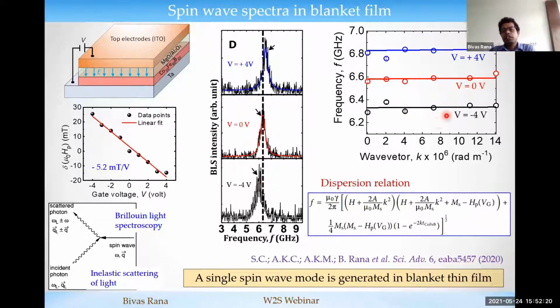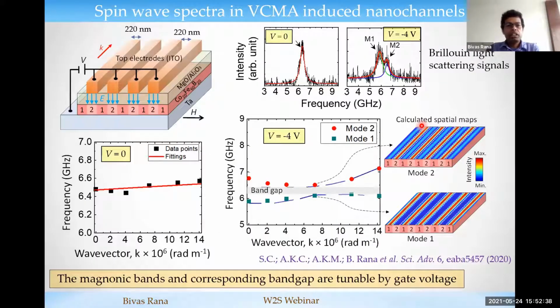Here is the dispersion relation at various gate voltages. You can see the dispersion curves are rather flat. That means the group velocity of the spin waves is quite low, because this is an ultrathin film. Now what happens if we make the channels? To do that, we made the top gate electrode like a stripe, where the widths are 220 nanometers and they are separated by 220 nanometers. Then we applied the gate voltage in the system. When we didn't apply the gate voltage, it behaves like a blanket film, so we get a single frequency, a single spin wave mode.